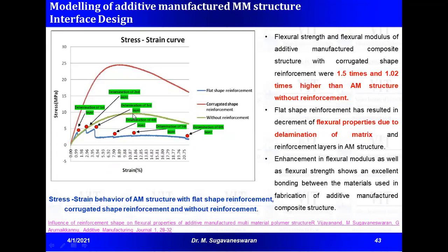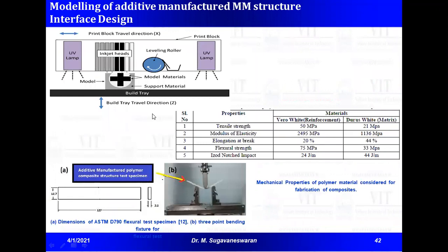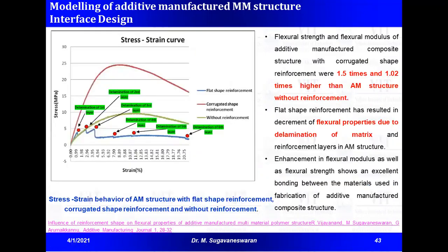Whereas in corrugated structure we could achieve a drastic increase from 10 megapascal to 25 megapascal, and that layer by layer fracture problem is also addressed by means of this corrugated structure, though it is not fixed at both ends. We could report the result until this part. So the interface problem based on the CAD design, the multi-material structure interface can also be designed for additive manufacturing, which is exclusively for multi-material structures fabricated through additive manufacturing.